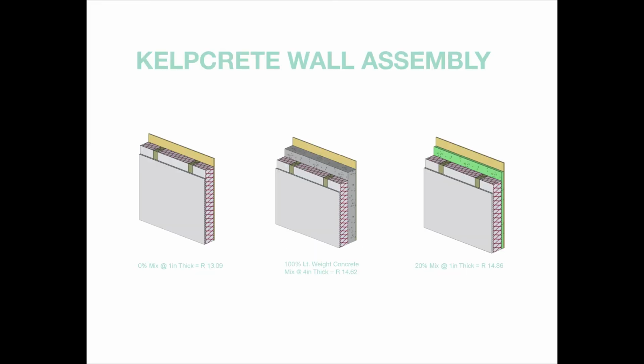The R value of kelp in our model based on existing installation samples using Opaque. These simulations are to show a kelp alginate infused concrete panel as part of a larger wall section and isolate its R value with other materials in this section. The figure on the left is 0% mixture at 1-inch thickness, which was the R value of 13.09. The middle figure is 100% lightweight concrete mix at 4 inches thick, and the R value was 14.62. The figure on the right was a 20% mixture at a 1-inch thickness, and the R value, which was the highest, at 14.86.